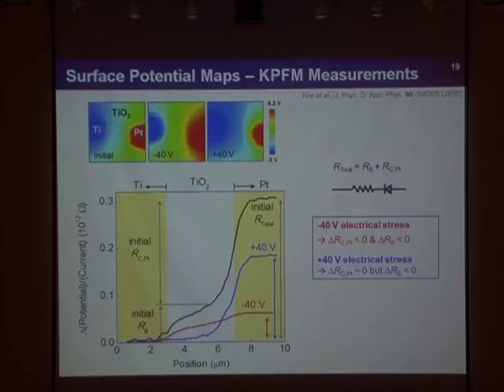So here I obtain the surface potential maps, from which we can estimate the contribution of contact and bulk resistance. In the initial device, there is a large voltage drop at the platinum-titanium oxide interface because it forms a Schottky contact, and very small contact resistance from the titanium contacts. The other portion corresponds to the bulk resistance.